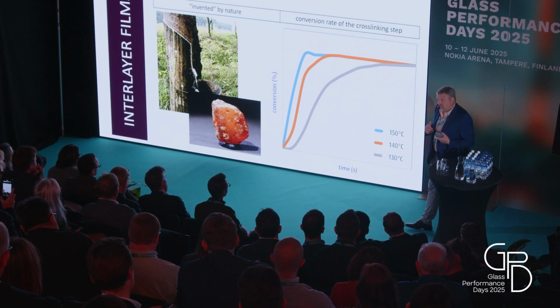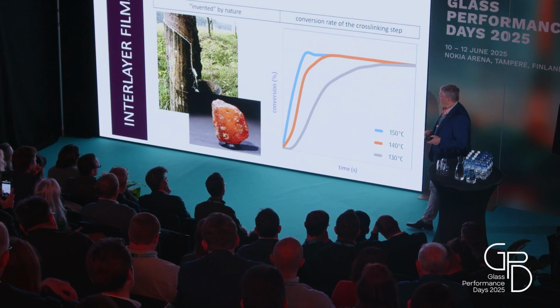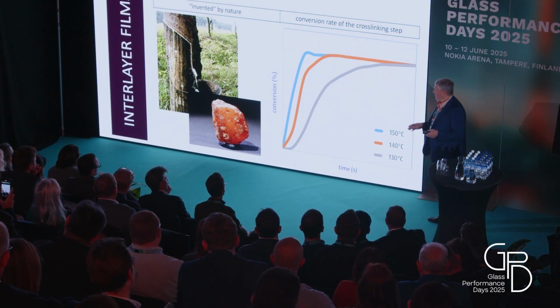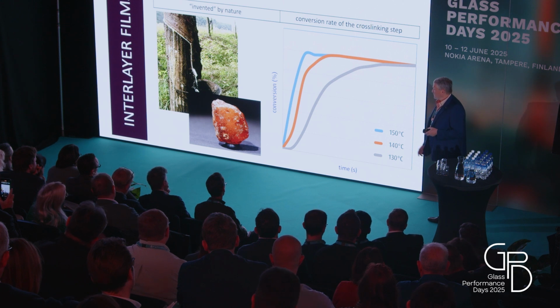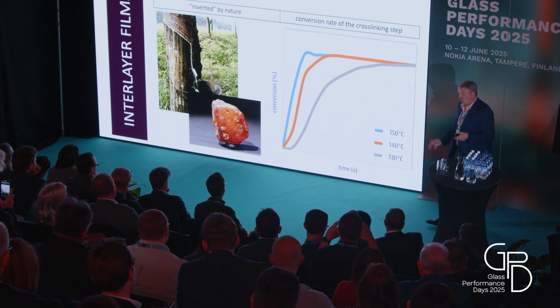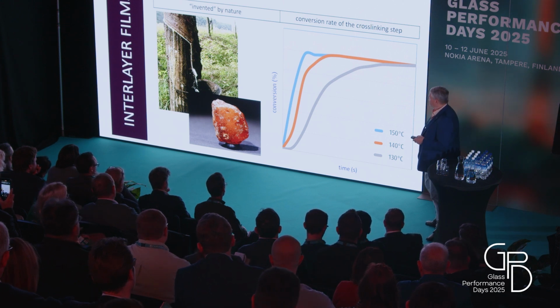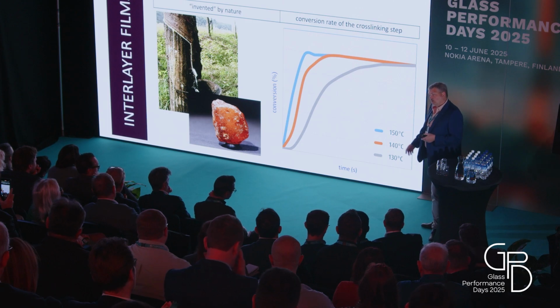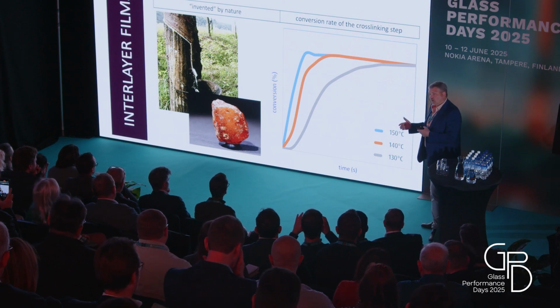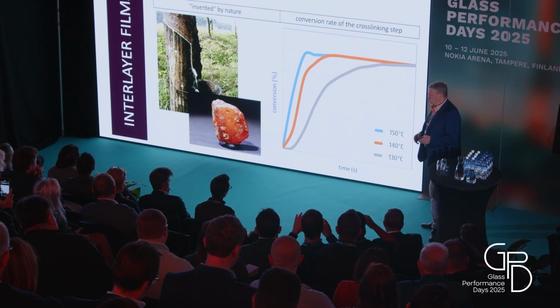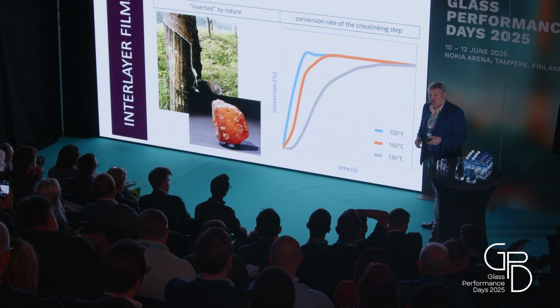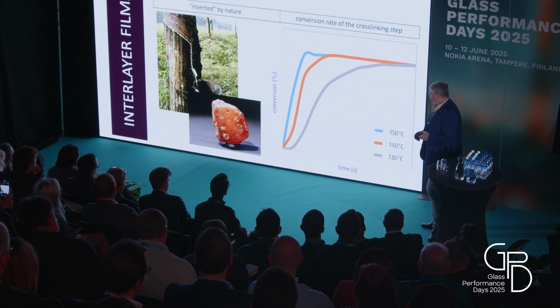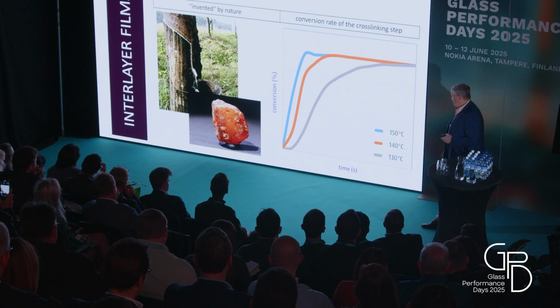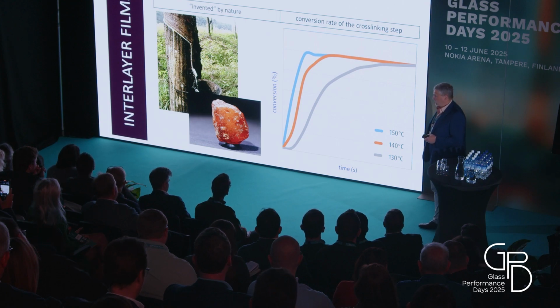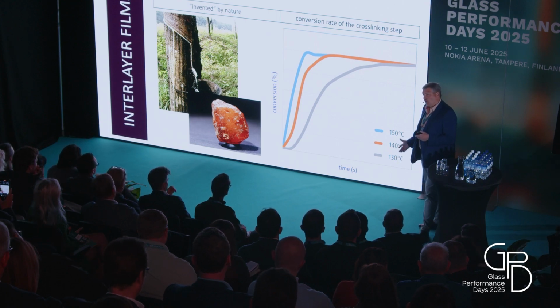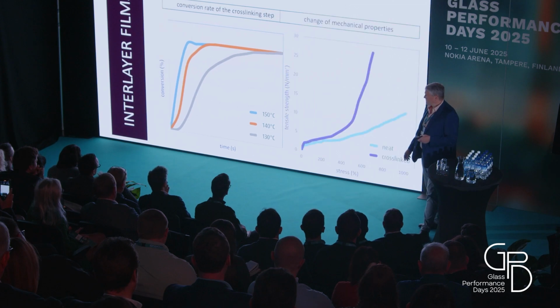We don't have so much time, therefore, of course, we have this special kind of additives in the interlayer film, and you can see here a conversion of the cross-linking over time for different temperature. It is well known that this process is temperature-driven. The higher the temperature, the faster the process is going. And you see here typical temperatures that we have in lamination process, 130 to 150 degrees C.